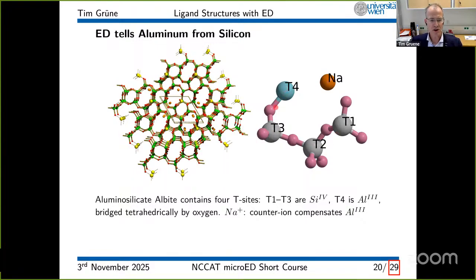Aluminum and silicon are very close in the periodic system of the elements. Silicon has Z is 14 and aluminum is 13. So they differ by only 1 electron. And if silicon is replaced by aluminum, then you need a counterbalance. In this case of albite, this is a sodium atom, which is balancing the charge introduced by the aluminum in this place. This is, again, a porous material, similar to a MOF, for example, but in this case, it's built of aluminosilicates of these tetrahedral building blocks.